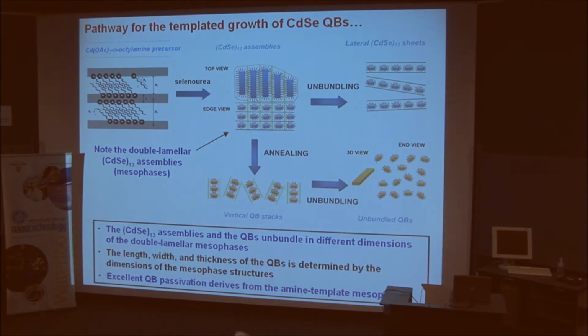So this puts it all together: the precursor in octylamine forms a lamellar template. And the lamellar template ultimately guides the dimensions and the morphology of the CdSe nanostructures that grow. And so initially, we grow double lamellar structures containing CdSe 13 nanoclusters, which are the little orange dots in this slide. So if we see this from the top, we see these vertical stripe domains. From the end, they would be stacked up in bundles like this.